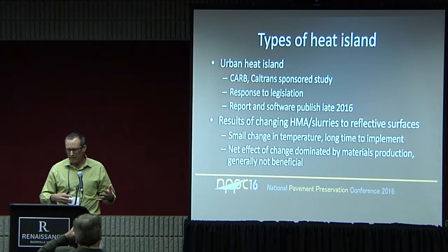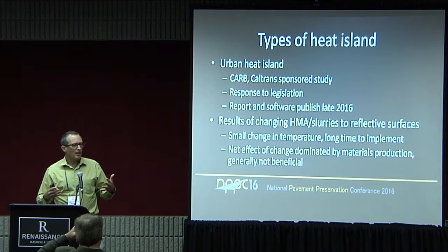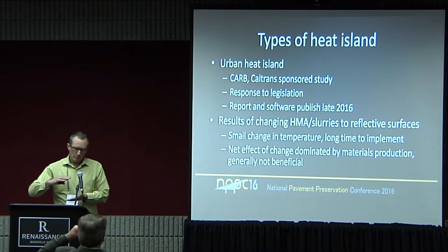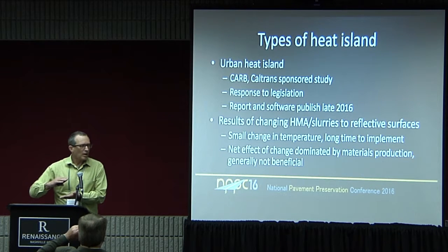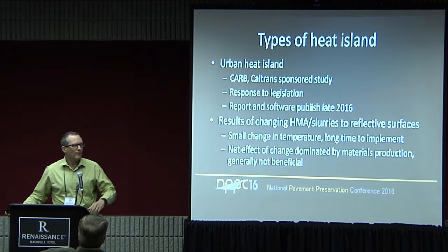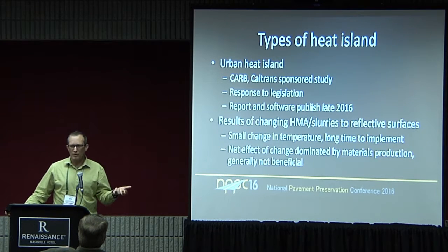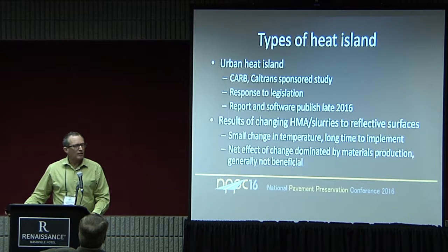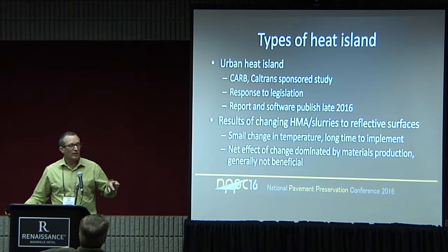What we found was that the impacts of, if you use that much concrete, not thick concrete, but 4 inches of concrete everywhere, switching the network over to that, the materials production effect on greenhouse gas was between 10 and 1,000 times greater than any savings from air conditioning use.